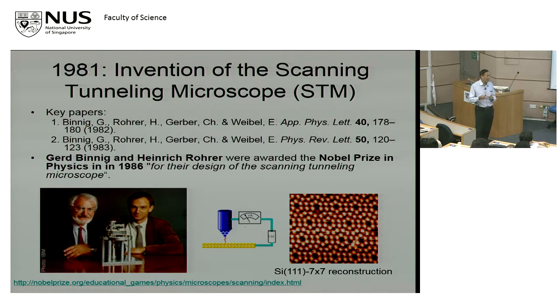But most of the time, it corresponds to where the atoms are. And you can do some experiments to try to disentangle the electronic and physical topography. But you imagine if you have a tip scanning the surface atomically sharp, you can not only get an image, you can do many things. You can get spectra, you can do IV curves on it, I'll show some later. But you can also use a tip as a probe to move things around, right?